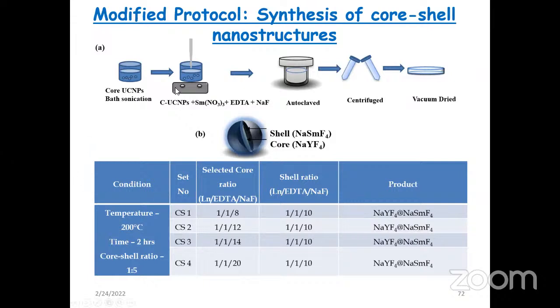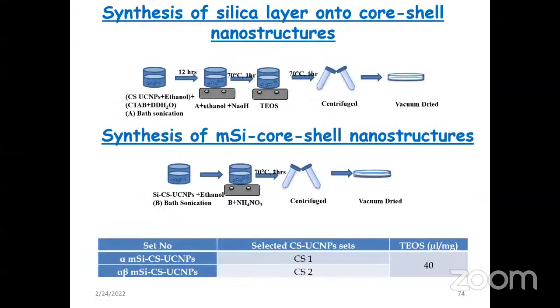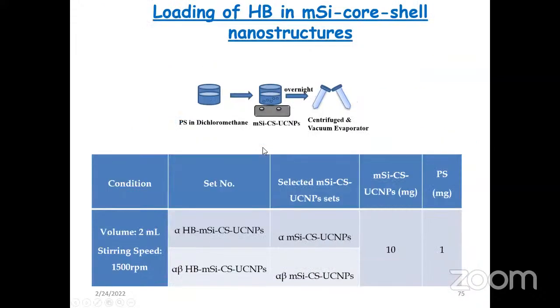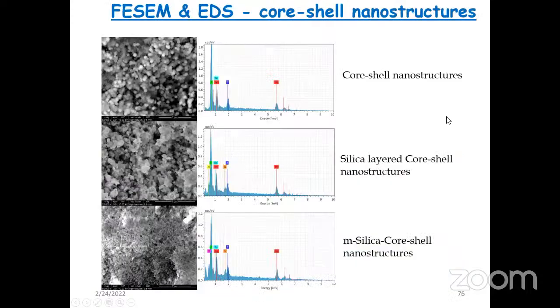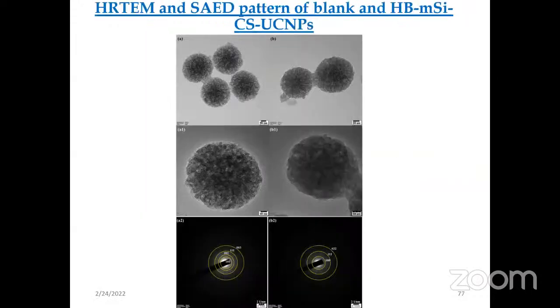After the synthesis of the core-shell nanoparticles, we coated them with a silica layer, for which we added silica. Once we made the silica layer, we made it mesoporous. After that mesoporous silica, we loaded the drug on it. These are the pictures of your core-shell silica layer. You can see some core-shell nanoparticles over which we have produced a silica layer. After making the silica layer, we made it mesoporous. Due to these mesoporous conditions, we were able to load the drug on it. This is a SAED pattern. You can see the structure where the porous nature is visible.